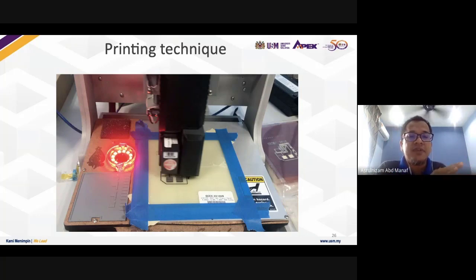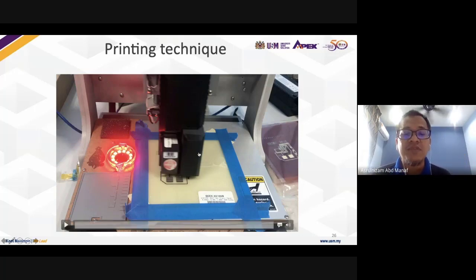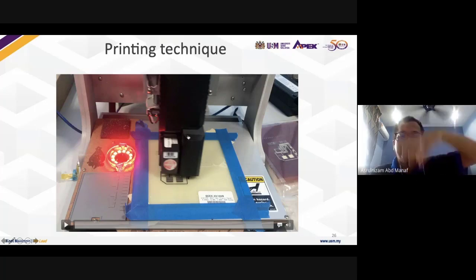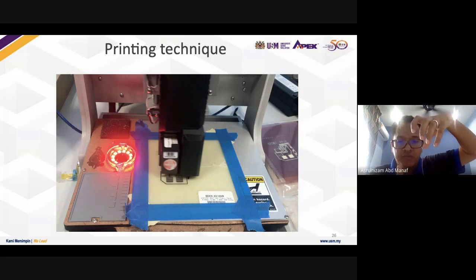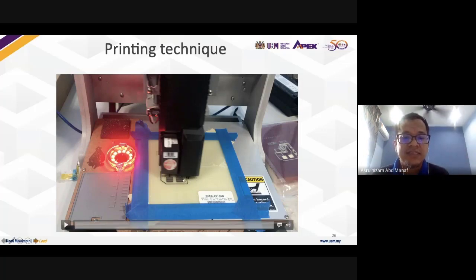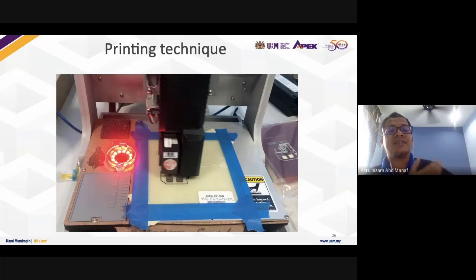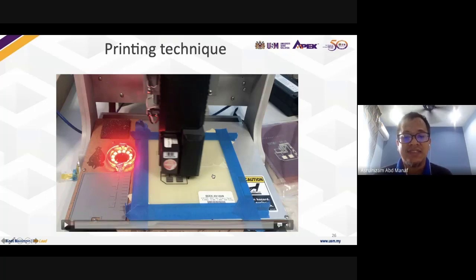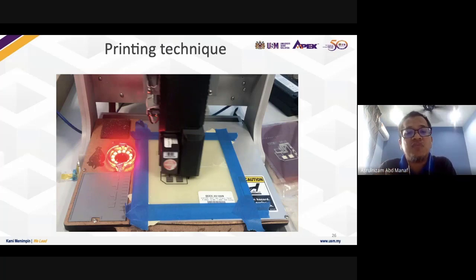But compared to inkjet, with screen printing you can waste the ink. Here you can minimize the volume. But the cartridge is too complex in terms of the sponge component, where you have to get the right volume of ink. If not, your ink will dry, right? And then the second, the size of the nozzle must be considered with your particle size, that means your silver particle size. And then also the viscosity and also the heater, the cure. Because the inkjet ink is not very viscous, if your cure is too slow, the ink can merge.